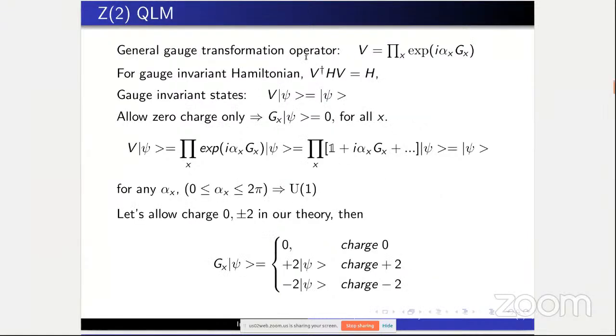Now the general gauge transformation operator can be written as V equals the product over all the gauge transformations at each lattice site x, where alpha_x is the gauge parameter and G_x is the generator of the transformation. For a gauge invariant Hamiltonian, we have V dagger H V equals H, and for gauge invariant states, we have to satisfy V psi equals psi. Now, if we allow 0 charges only, then G_x equals 0 for all lattice sites x. So it can be shown that for any value of alpha_x between 0 and 2 pi, this relation V psi equals psi is satisfied. So this is a U(1) theory.